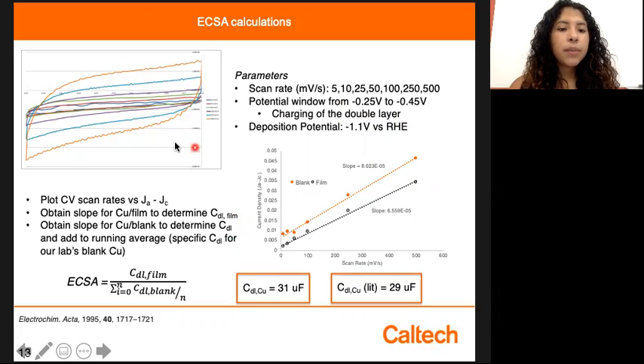Similar to the silver paper, we used the different scan rates and extracted the current from the center of the applied voltage window, then plotted the current densities versus the scan rate and used this formula to find our ECSA. To find the CDL value for our system, we took the average of all our blank copper electrode capacitance and found that our CDL was 31 microfarads, which is comparable to the literature value of 29 microfarads.